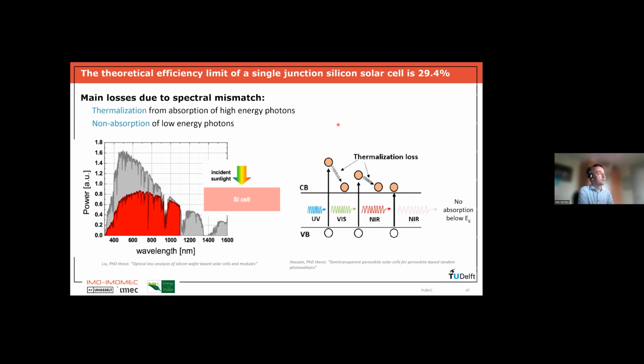So why is this? The reason is that we lose a lot of the energy of the incoming light, and it is because we have spectral mismatch. Silicon has a band gap of 1.1 eV. So all the photons that are incoming which have energy below the band gap cannot be absorbed. This part of the spectrum is already completely lost, but it's difficult to do something about that part. But even the photons that do have high enough energy to get absorbed, in the end we use only part of that energy, the red part, and all the gray part is lost.